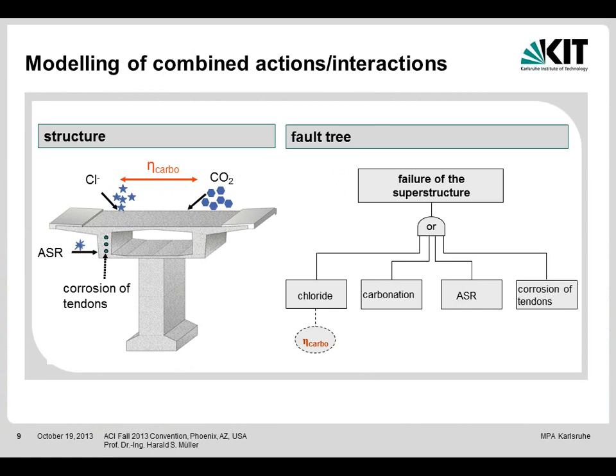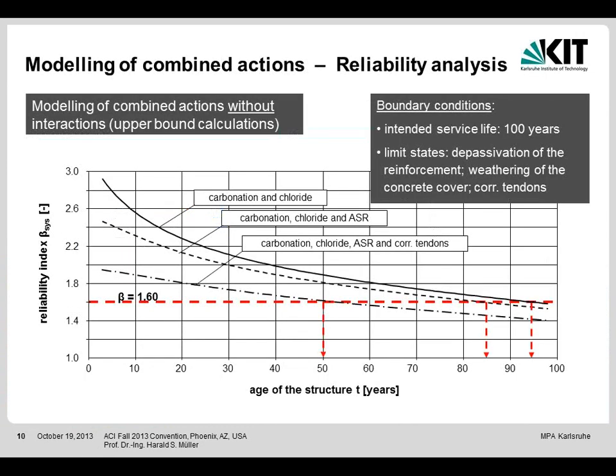But they interact. And there is a further parameter, just a simple one. We know that chlorides and carbonation have a particular interaction. Carbonation may release chlorides which have been bonded before. So doing this calculation, we have to take those things into consideration, and this may actually be done. If we have no interaction, but different actions on different parts of our materials, this result is obtained by this design reliability, again, over the age of the structure.